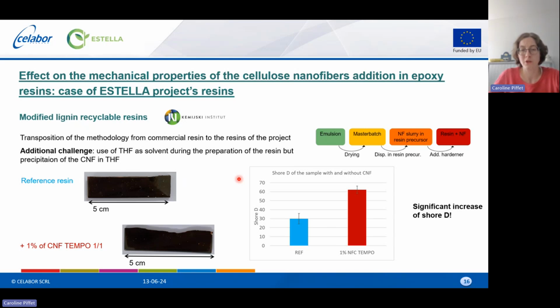And when we measure the Shore D of this sample, so to quantify the hardness, you can see a very significant increase of the Shore D, which is about twice when we add 1% of those nanofibers.